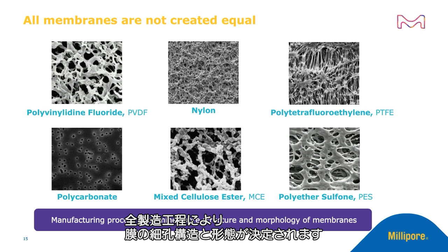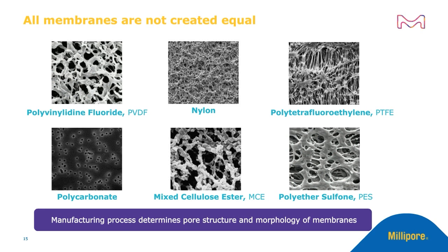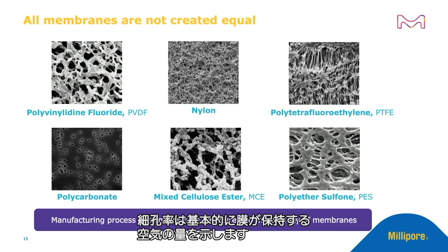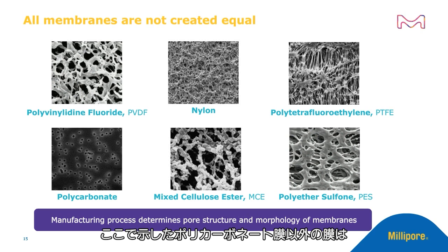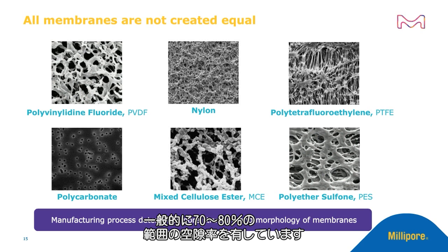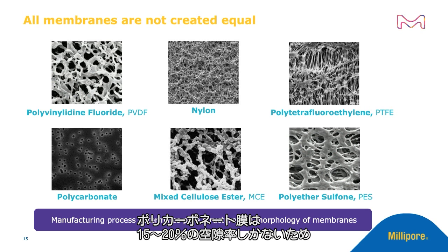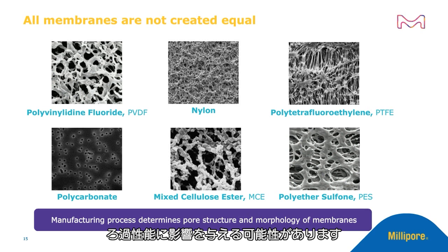The manufacturing process overall determines the pore structure and morphology of the membranes. Many times the porosity of these membranes also differs. Percent porosity essentially indicates the amount of air these membranes hold. Except for the polycarbonate membrane shown here, all the other membranes generally have a porosity in the range of 70 to 80%. The polycarbonate membrane, on the other hand, only has about 15 to 20% porosity, which can impact its filtration performance.